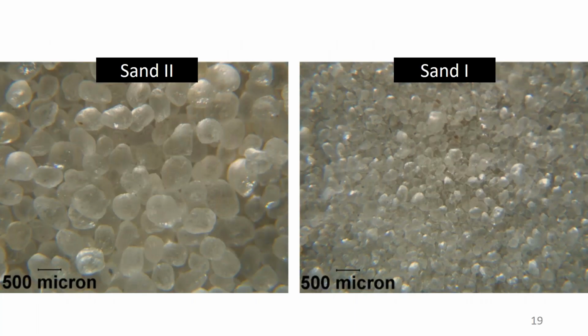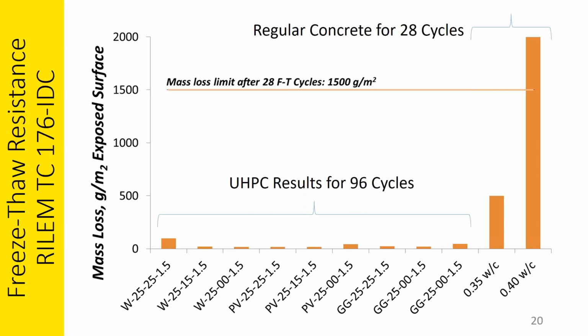These are the sands that I mentioned. On the left is the large particle sand. You can see again how big 500 microns is. This sand typically would have a median size of about 600 to 800 microns. The finer sand on the right is about 150 to 200 microns. According to packing theory, this fits in between the larger sand particles, fits very neatly in there, okay?